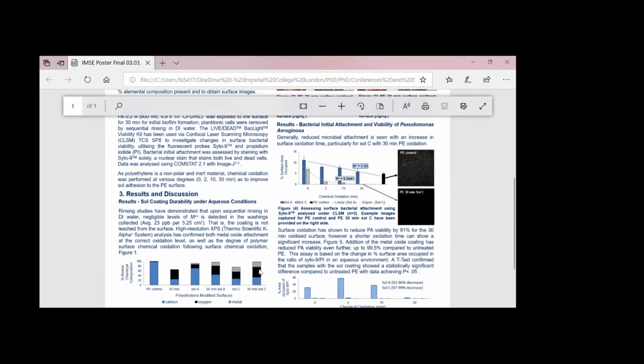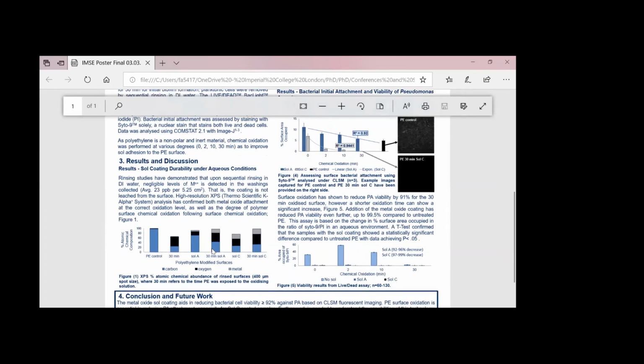Moving on to some results. Leaching studies have shown that negligible amounts of metal are leaching off, well below the safety limits for this metal oxide. And the XPS results are shown here, where you can see there are significant modifications that have occurred to the material after treatment, including oxidation treatment and coating of the metal oxide.